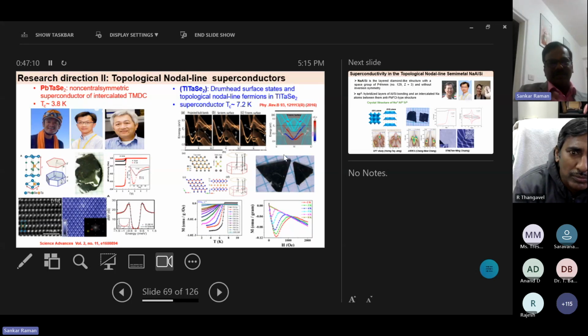Why do I specifically show you the CVD technique? Because we recently grew some topological nodal line superconductors. Lead tantalum diselenide is a non-centrosymmetric topological nodal line superconductor. In the physics community, people found it very difficult to grow this single crystal. One of the main single crystal pioneers is R.J. Cava. He made the powder, but he claimed we cannot grow the crystal.